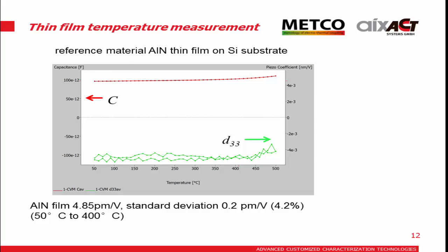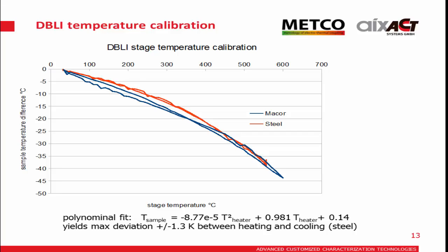Also for PZT characterization, some effort was taken into temperature calibration, as we also have seen before. We took a commercial stage, and we were surprised that there's a huge difference between your actual heater stage temperature and the sample.